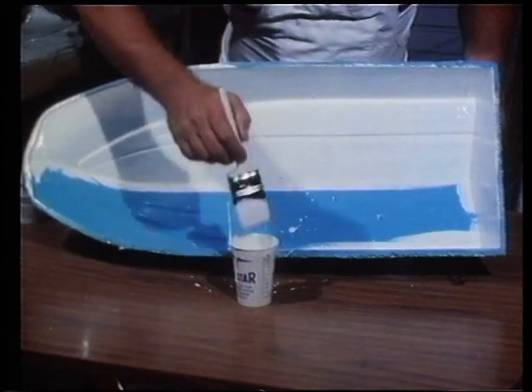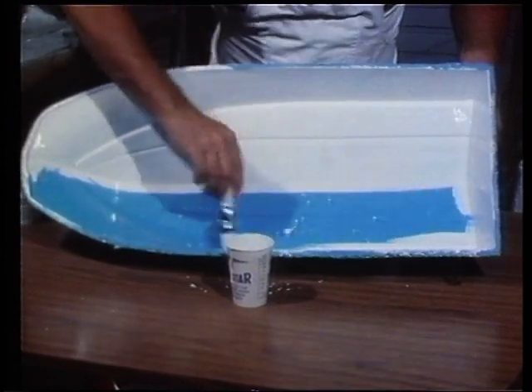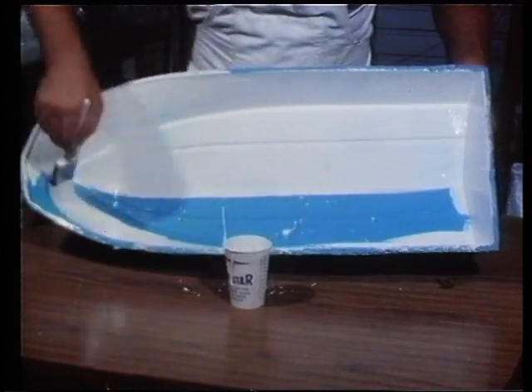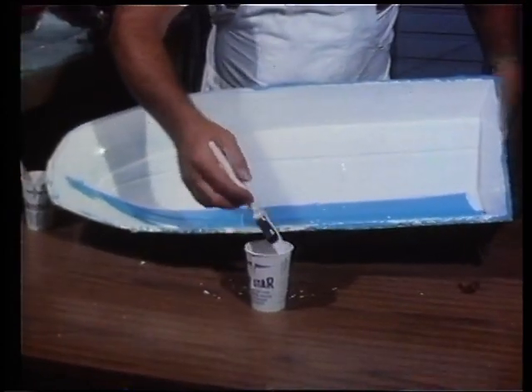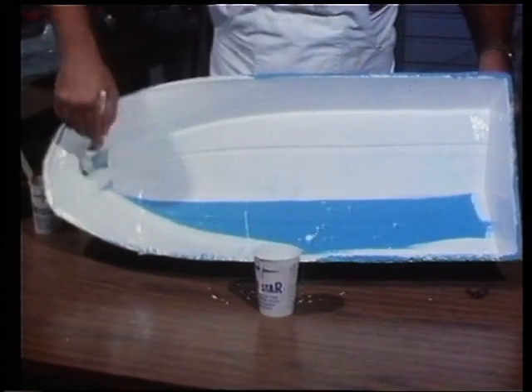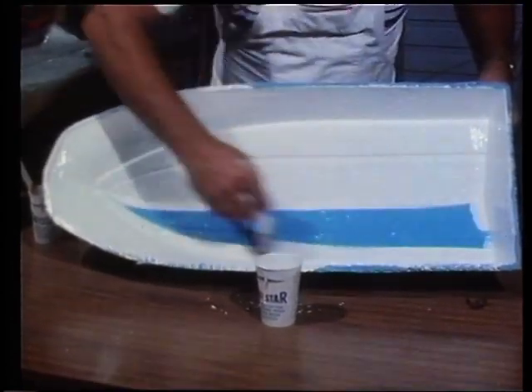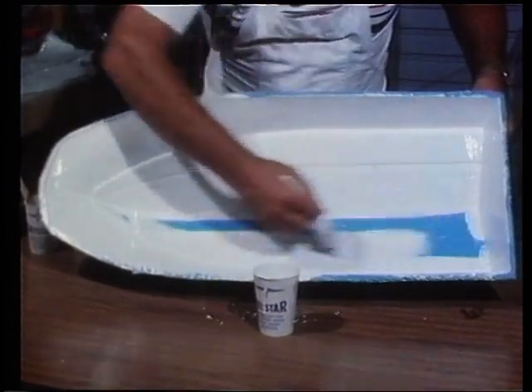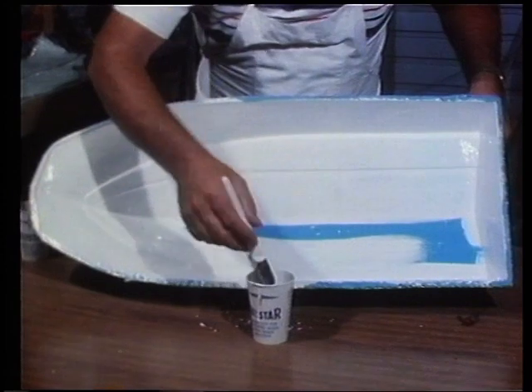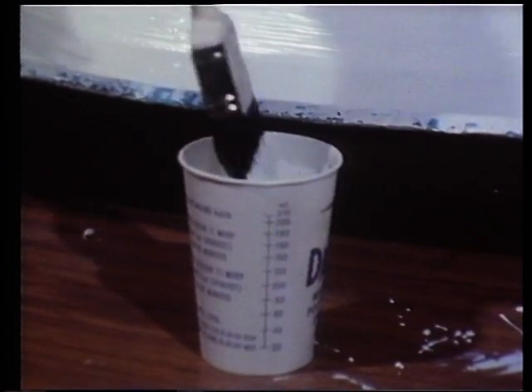Now you'll notice that I'm continuing to load that brush up and continuing to spread the gel coat all over the inside of the mould. At this stage, because I've just stirred it, it will flow quite happily and it's quite easy to brush. But a couple of minutes after I've finished applying it to the inside of the mould, it will what they call set up. It's not the curing process, but the thixotropy has been sheared by stirring it, and once it's still again on the inside of the mould, it tends to lock up and be difficult to brush. So you have to make sure that you are fairly rapid and accurate in the distribution of the gel coat.